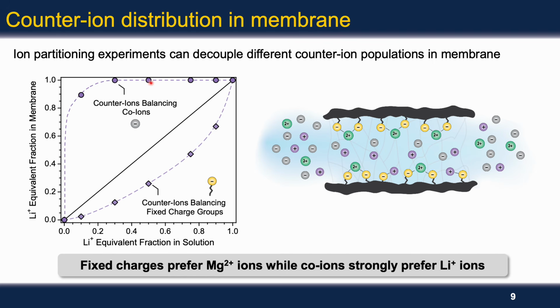preference for lithium ions. And to give you some numbers, at a lithium equivalent fraction in solution of about 0.3, the lithium equivalent fraction in the membrane for the coions is close to 1. So there's an exceptionally strong preference for lithium ions to move with the coions that govern concentration-driven transport.